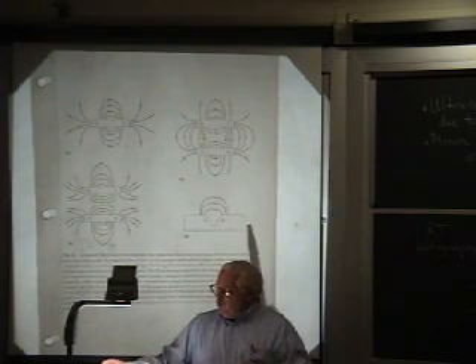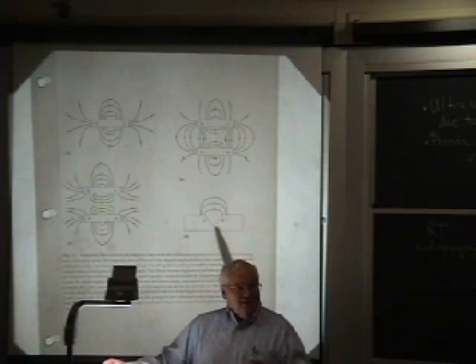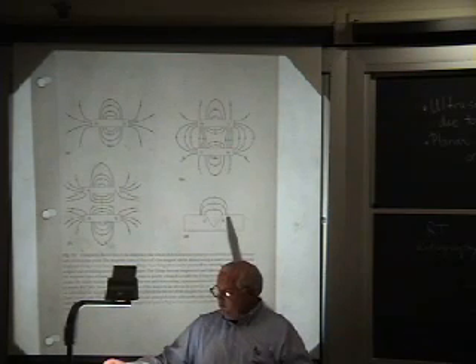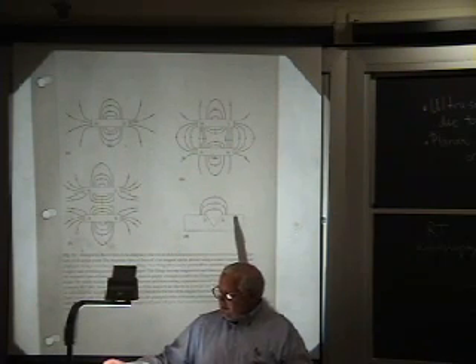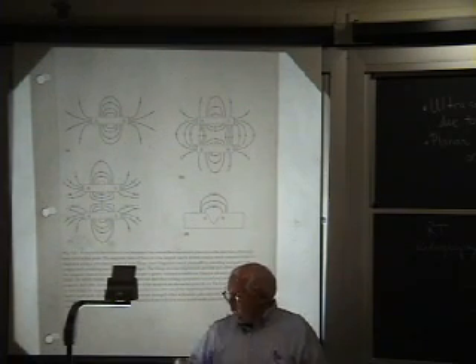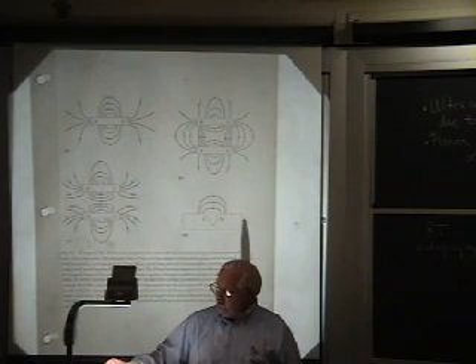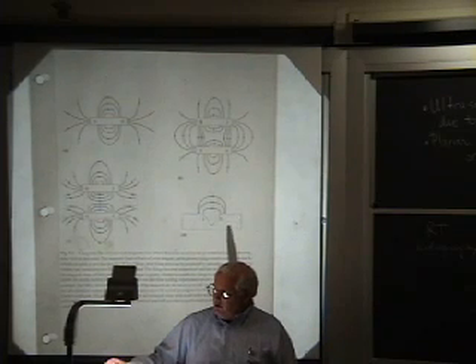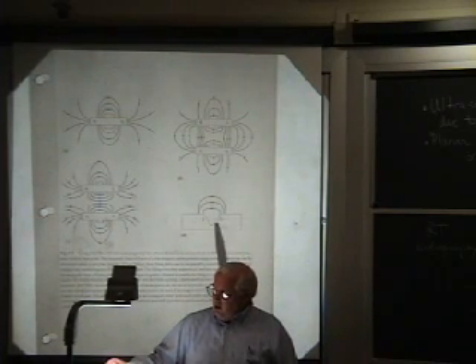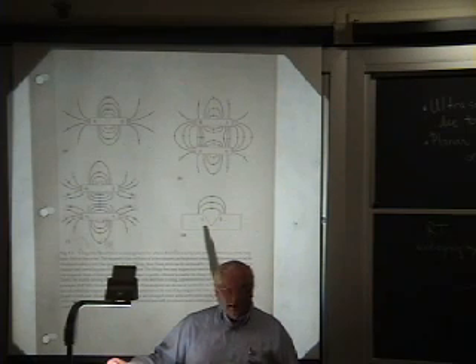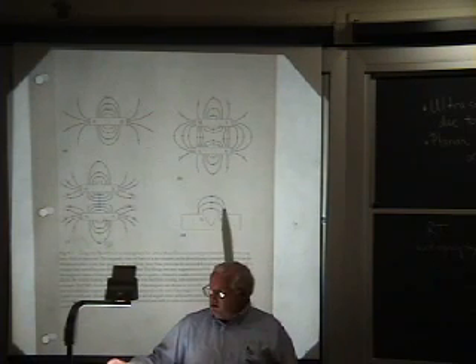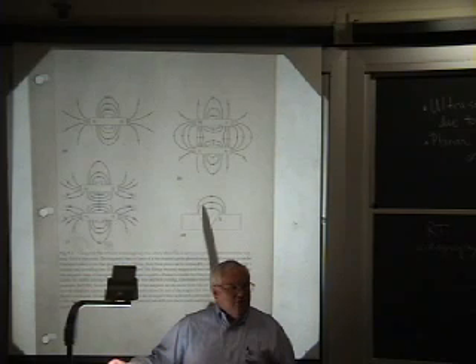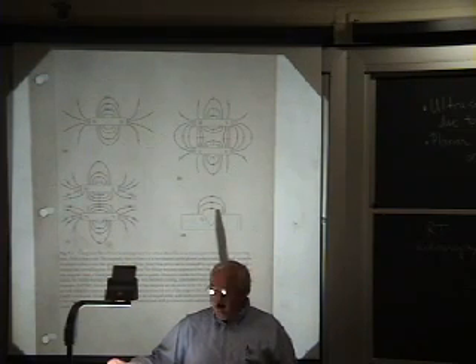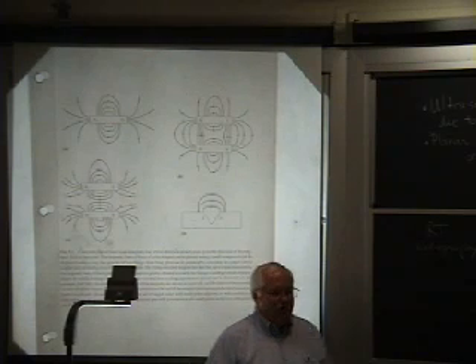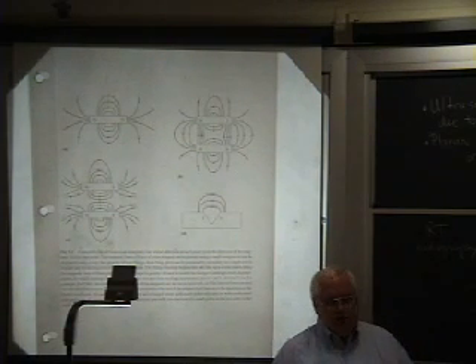So you try to saturate the material with magnetic field, and if you have a notch or a defect, and it doesn't always have to be exposed to the surface, it can be just below the surface, then since you're near saturation up in this region where everything's solid, but you get over here and the flux lines get too crowded, you get too high a density as they're all trying to go around that corner, and some of them have to find their way outside. So some of the magnetic flux escapes outside the part into the air, and that non-uniform magnetic field is going to attract magnetic particles.